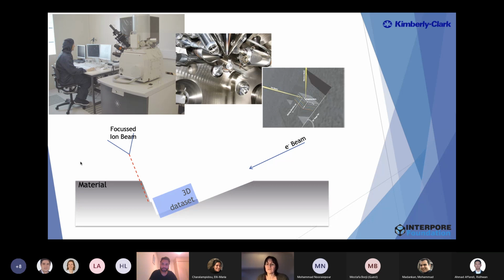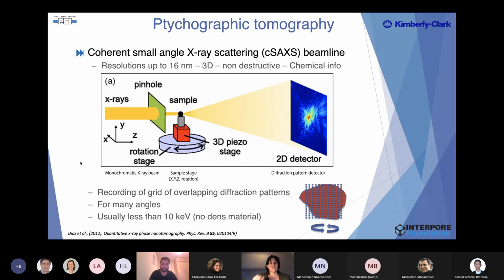So a technique we use if you want to go for high resolution 3D is coherent small angle scattering, also known as ptychographic tomography. This can be done, for instance, at the cSAXS beamline at the Paul Scherrer Institute in Villigen, Switzerland. There they can reach resolutions up to 16 nanometers in 3D, non-destructively, also allowing you the possibility to obtain chemical information. The way it works is that you have the synchrotron and you record overlapping diffraction patterns for many angles as you scan your material.